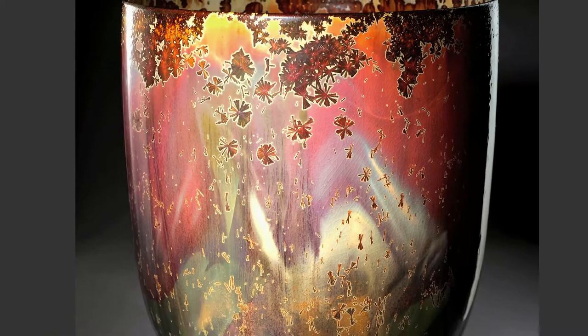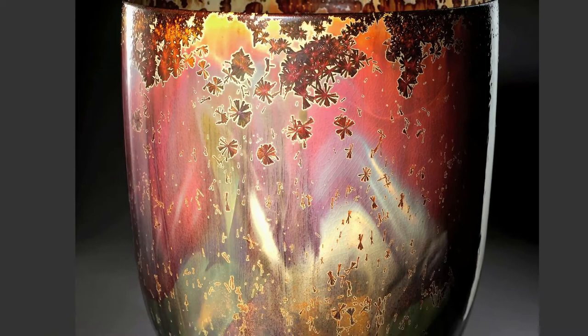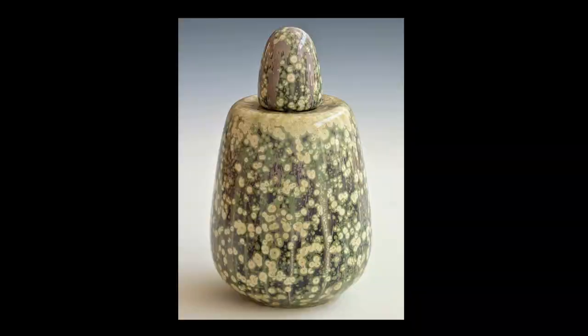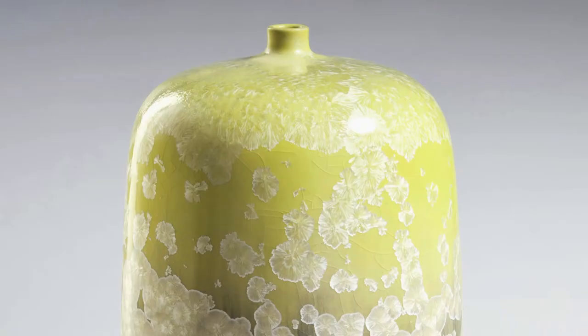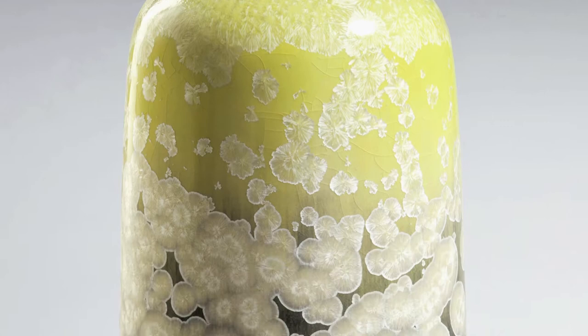The metal oxides include copper, cobalt, silver, tin, and iron. Depending on what percentage you add you'll get different colors and color variations. The glazes run quite a bit, so on most glazes I'll apply numerous glazes down the pot and let one glaze melt into another, so one color melting into another creates all these color gradations on the same piece.